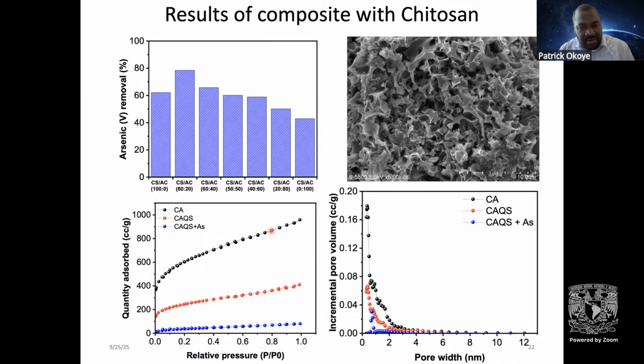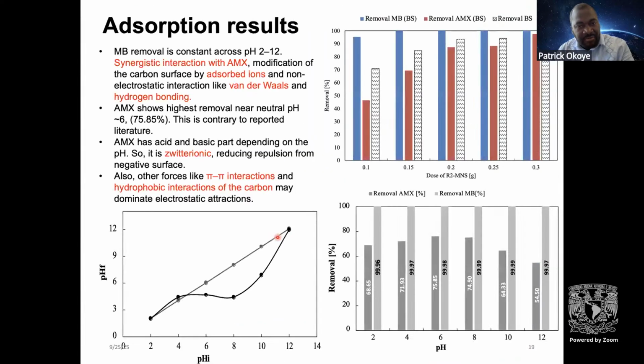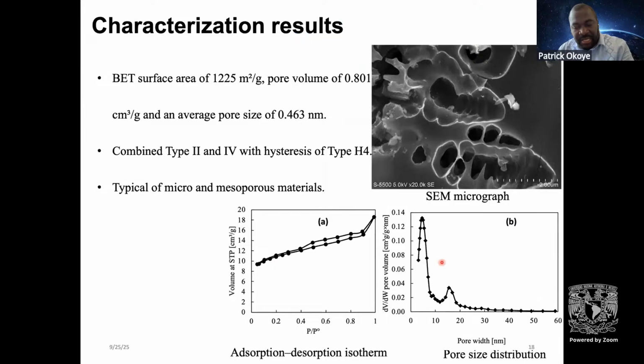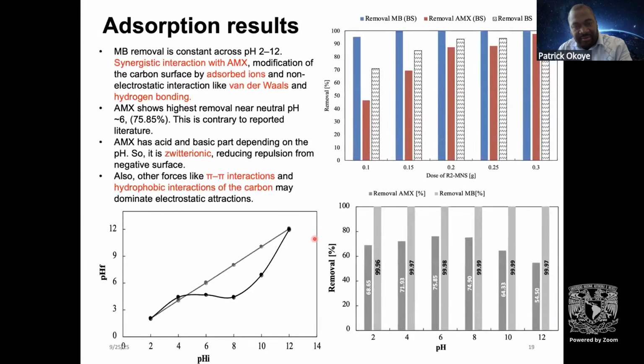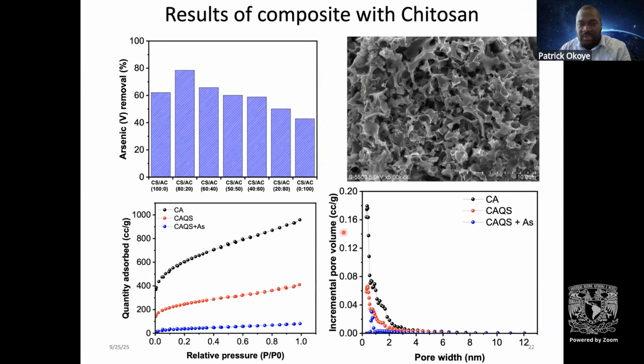And from here, you could see that the isotherm is way different from what we had from the last one. This isotherm does not have a space in between, so there is no hysteresis happening. This is another type of isotherm. They call it a type 1 isotherm, with pores even far narrower, in the micropore region.